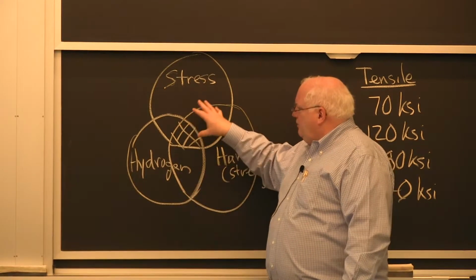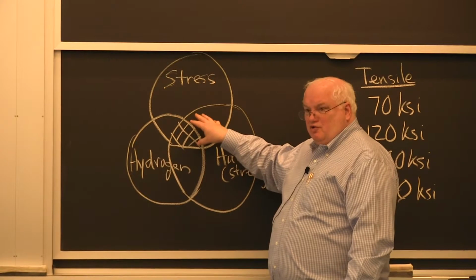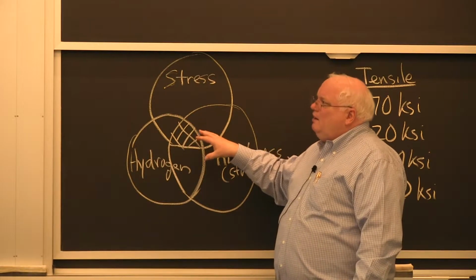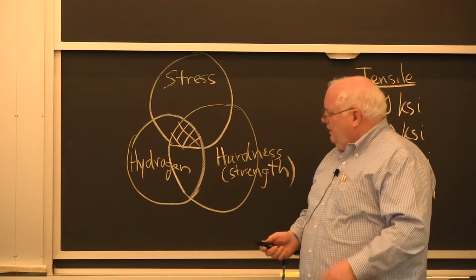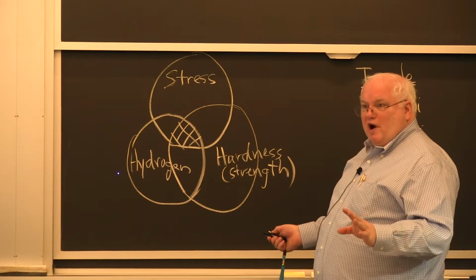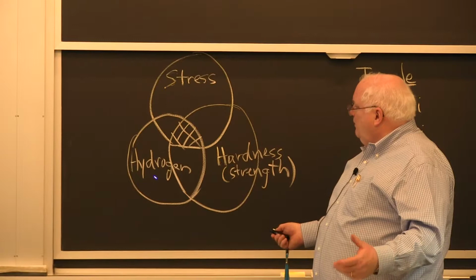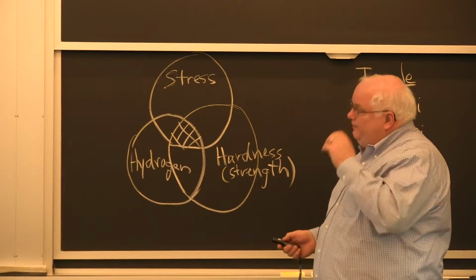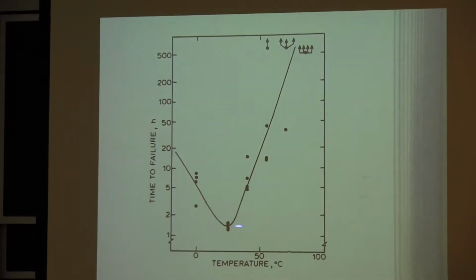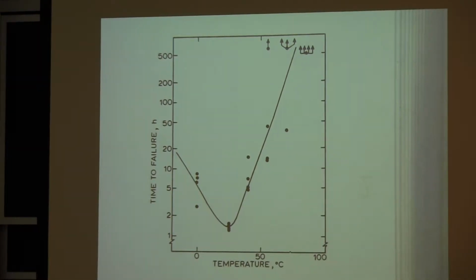So at a higher level, this at a lower level, this is hydrogen stress corrosion cracking, but we don't usually call it that. Sometimes people do. But again, hydrogen stress corrosion cracking would occur at the cathode, whereas most corrosion occurs at the anode. In any case, this is time to failure versus temperature, and this is real data points in hydrogen sulfide, and it shows that the minimum time to failure is right around 25 degrees centigrade, and lo and behold, it's just over an hour. So why do you have to get into the furnace within an hour?